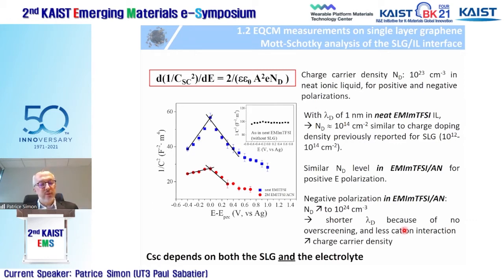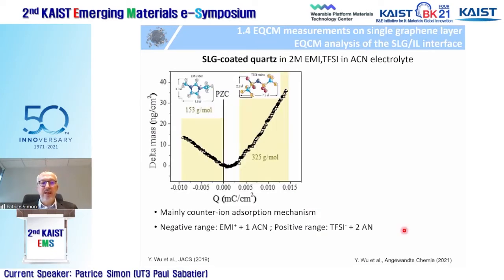So what is super important to understand is that the space charge capacitance and the capacitance of a single graphene depends on both the graphene and the electrolyte. And if you do gravimetric analysis, like I mentioned before, weight change versus Q, then you can see that on both sides you have counter ion adsorption. If you inject negative charge, this is balanced by adsorption of cations. You inject positive charge, this is balanced with adsorption of anions.